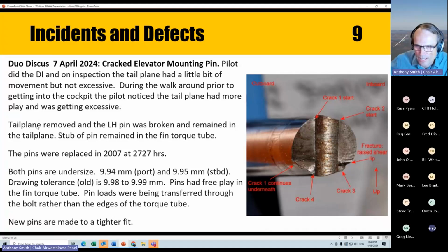I'll also point out a couple of features. There were 4 cracks that I found. The original crack was crack 1 on the left-hand side. An interesting feature is that it grows underneath and much further than the crack that intercepts it, which is crack 4. You can see that there was water sitting in the bottom of the crack at various stages to enable it to trap a bit of dirt and corrode, which is what those brown marks are on the left-hand side.